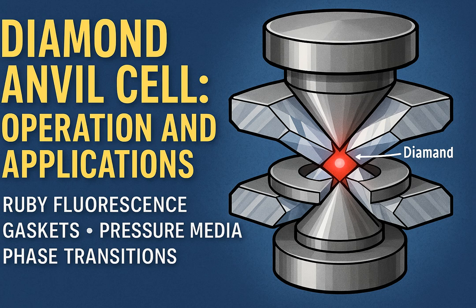Okay, pressure covered. What else can you probe inside the DAC? You mentioned AC susceptibility. Yes, AC susceptibility. This measures how a material's magnetization responds to a small, oscillating magnetic field. It's great for detecting magnetic phase transitions, like a material becoming ferromagnetic or superconducting. You use those tiny coils we talked about, connected to sensitive lock-in amplifiers outside. But interference must be a huge issue. Oh, absolutely. It's critical that everything near the sample, the gasket, the backing plates, the epoxy, even tiny impurities in them, is non-magnetic. Even a minuscule ferromagnetic impurity, maybe in the gasket material like rhenium or tungsten carbide, can create a background signal, especially one that changes with temperature, potentially masking the real signal from your tiny sample. You have to carefully test all your components beforehand.